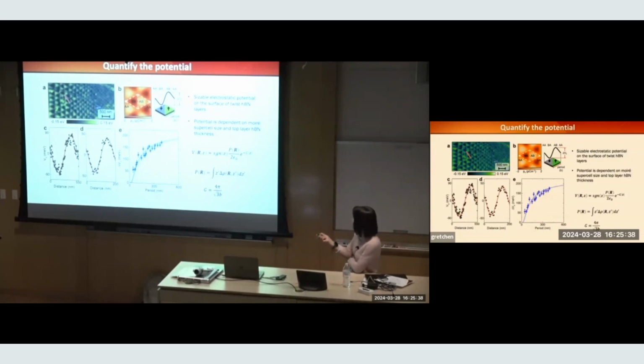So I can actually take a line cut. I can measure the surface potential. By the way, the thinner the hBN, the deeper the potential will be because the spontaneous polarization forms at the twisted interface. Monolayer, bilayer hBN is really hard to find because they're very transparent, okay? So we didn't bother too much with that. The results I'm going to show you are all hBN layers 5 nanometer, 7 nanometer, or even 12 nanometer thick. They're pretty thick by the standards of people working in this field.